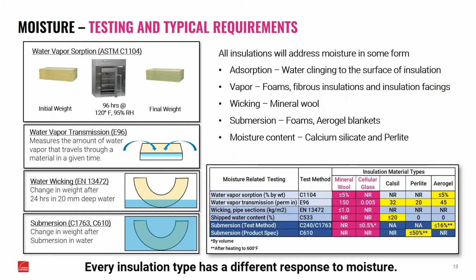Another thing that we look at is water vapor transmission. Although you won't have an insulation type that has this requirement, you'll see this associated with insulation facings. One of the reasons we care about this is that a facing is usually going to have a very low perm rating, because you don't want a lot of moisture going into that system if you have a chilled water line. Now, the other part about this is that the higher the perm rating, the faster the insulation will dry if it does get wet, because water vapor can more easily pass through something that has a higher perm rating. It's about the amount of moisture that will pass through something in a given period of time.